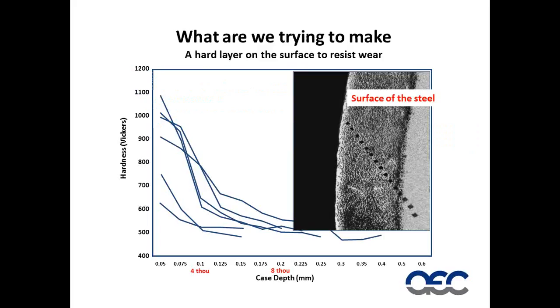What are we actually trying to make? Well, if we look at the picture on here, you're looking here at the surface of your steel. This is the outside edge of your die. This is the hardened layer we're trying to create, and this is the base layer of steel underneath. And these little marks you see, little squares, these are the indents from a Vickers micro hardness indenter, which is a square pyramid driven into the surface.